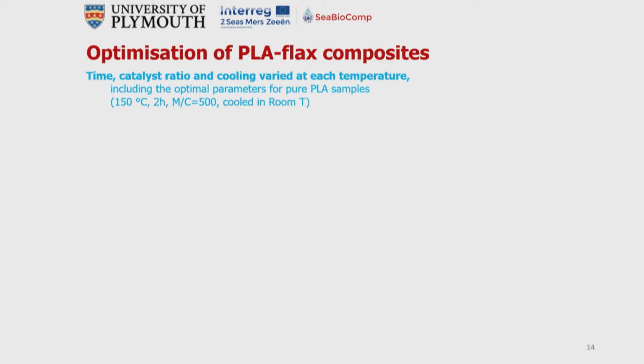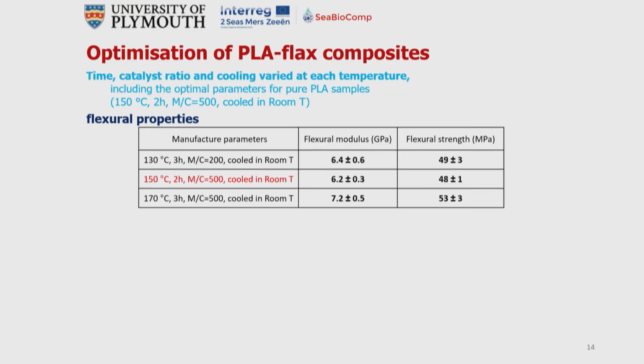We looked at the optimization, the time, catalyst ratio, and cooling varied at each temperature, including optimal parameters for pure PLA, and identified that 150 with a catalyst ratio of 500 was given as the lowest modulus and the lowest strength.